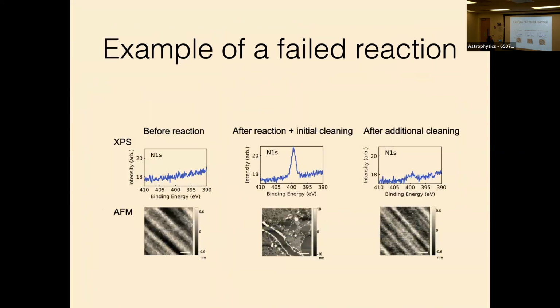So here's an example of how this pipeline works. This was a reaction where we were trying to put a nitrogen-containing group on the surface. Before the reaction, you see no nitrogen in XPS, and the AFM gives you this nice smooth surface with just these polish marks. And then after the reaction, you see this nitrogen peak. So yay, it looks like we have nitrogen. But then if you go to the AFM, you can see that there's just all this junk on the surface. One thing that really helps you here is that if you have non-specific binding to the surface, the probability that it gives you a perfect monolayer that's totally conformal is essentially 0. So most things will actually show up if you just take a look. Then if we try to clean it to get it to a stage where it looks clean, you can see that this nitrogen peak goes away, and that means that this was a failed reaction.